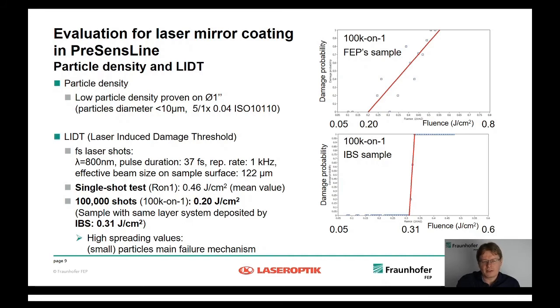It's not a bad value, still a bit lower than what Laser-Optic observed with the IBS sample, 0.31 joule per square centimeter. You can understand this difference when you see these curves here. The IBS sample has a very narrow distribution. This crossing point is actually the LIDT value for the 100,000 shots. With our sample, we observed quite a high scattering of the values, and so this number was lower.